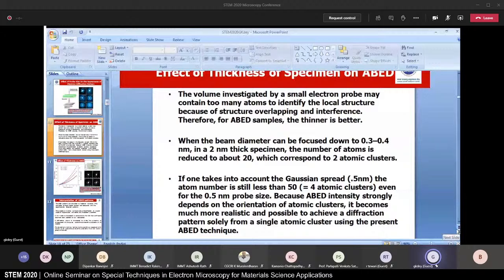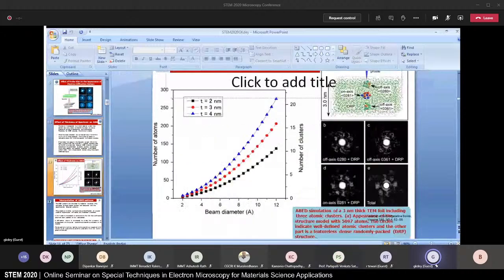So here we see the effect of the orientation. You can see that there are 3 clusters in the line of the beam, but only the middle one is oriented suitably, so it is contributing to the diffraction pattern. Then we see the importance of thickness.